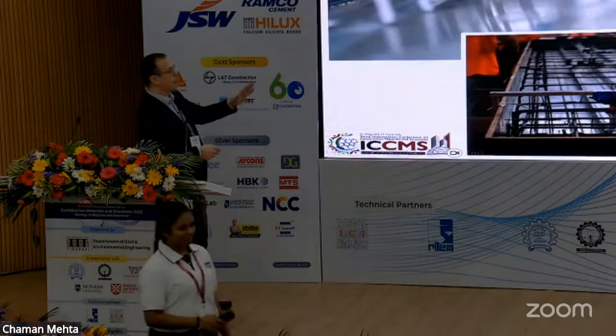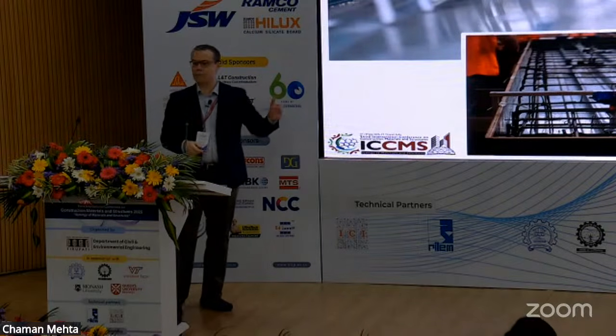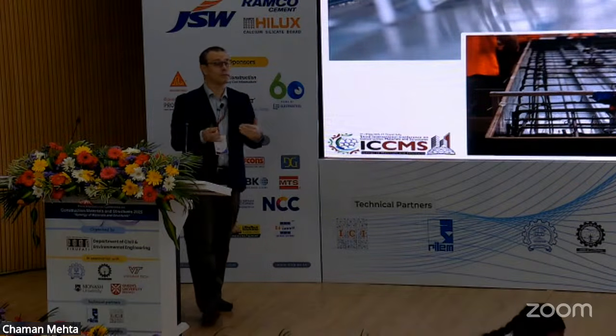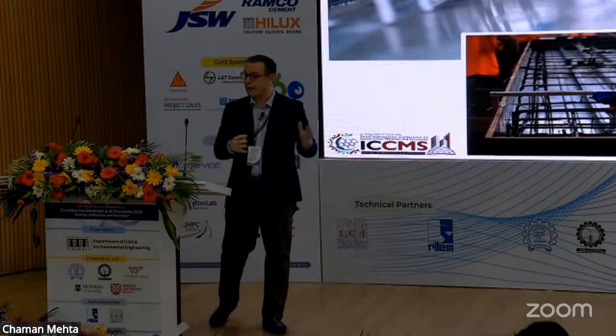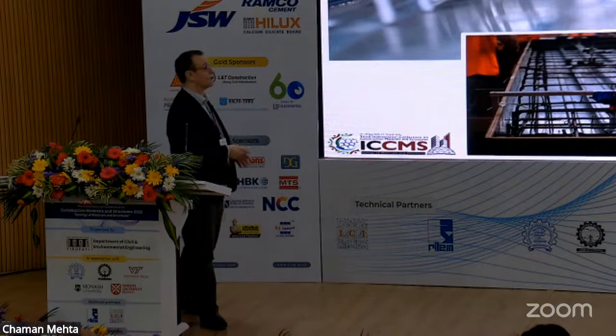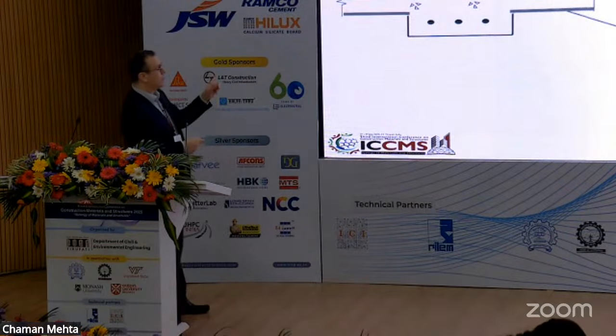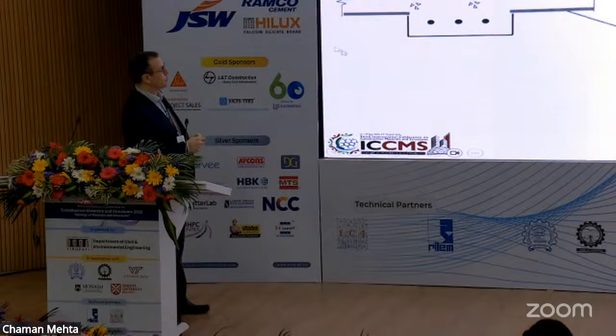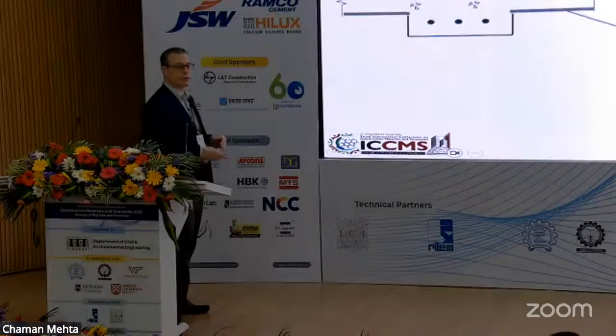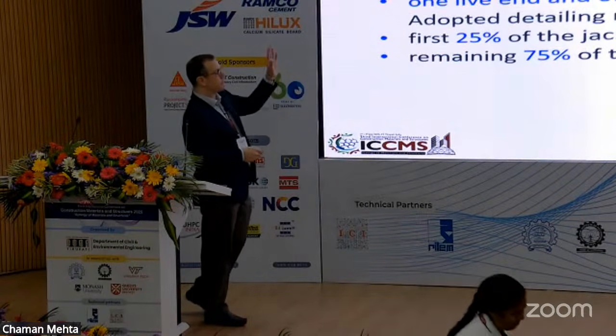As always, I like to show samples before casting, because there is a lot of work in the preparation of the samples, and we never actually shared it. Usually, once you cast it, it's gone, it disappears. In terms of details, what we did is to resemble the true detail of the steel deck on site. We stopped the sheeting before the support so that there was no friction between the sheeting and the concrete. And these are just the information for the setup.